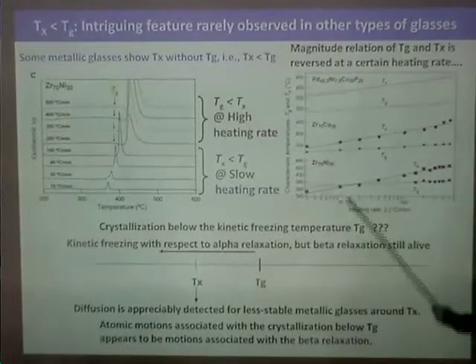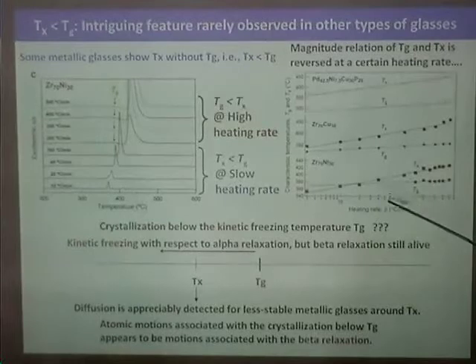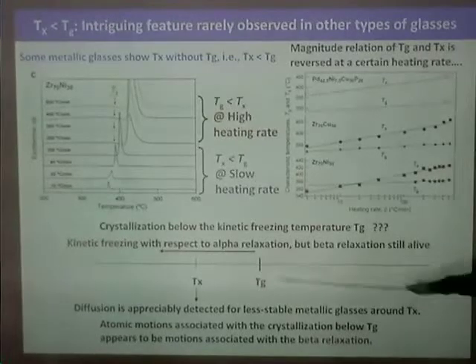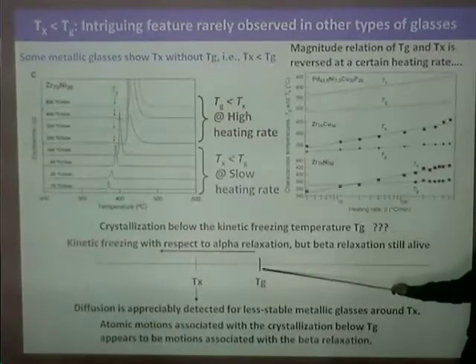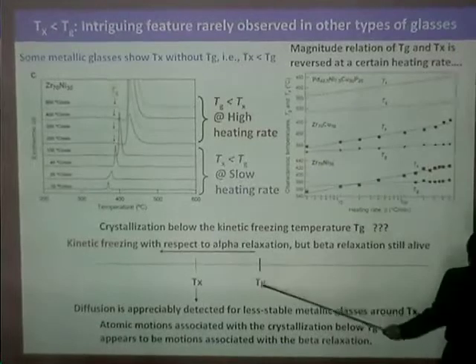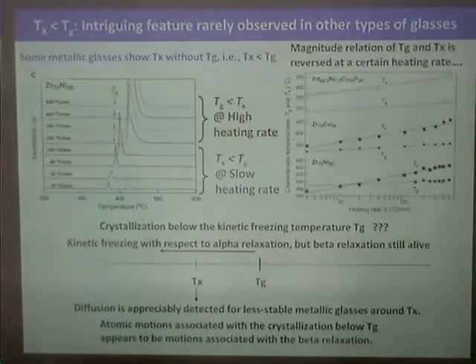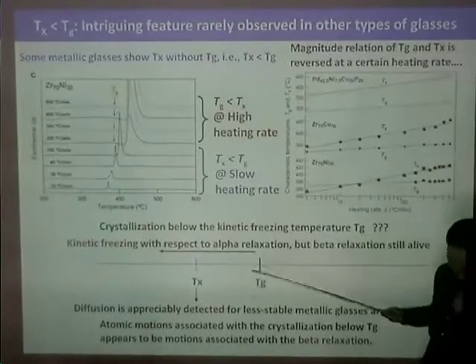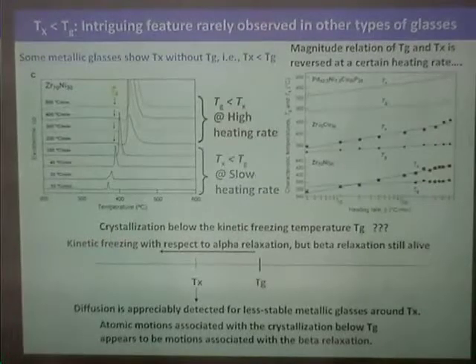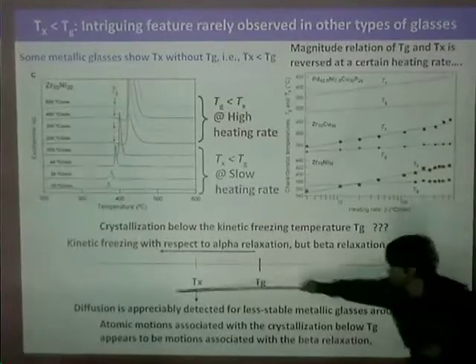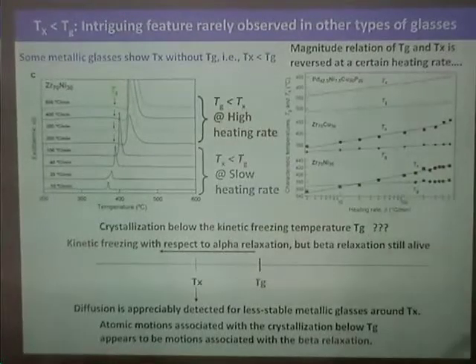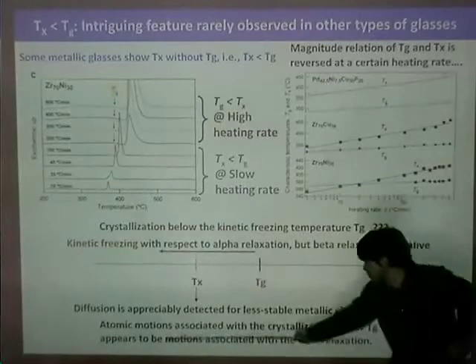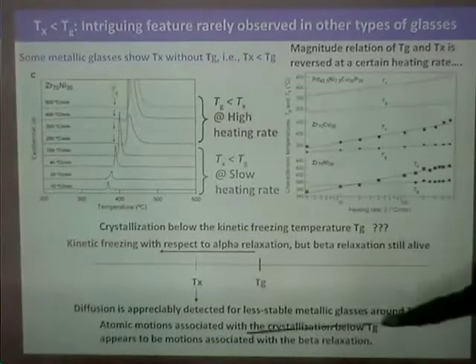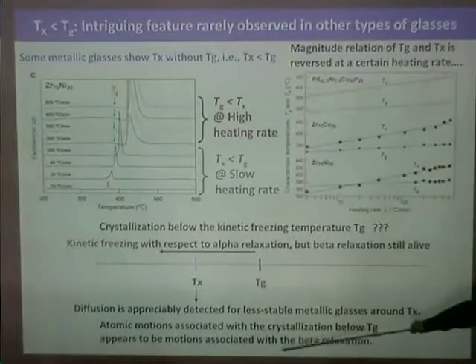This is very interesting for me, because kinetic freezing occurs below around the glass transition temperature, with respect to the alpha relaxation. Therefore, below the glass transition temperature, most of the kinetics is frozen. But beta relaxation, or faster mu relaxation, or fast beta relaxation, is still alive below the glass transition temperature. Therefore, such a crystallization is probably caused by the beta relaxation, because atomic motion associated with crystallization below Tg appears to be motion associated with the beta relaxation.